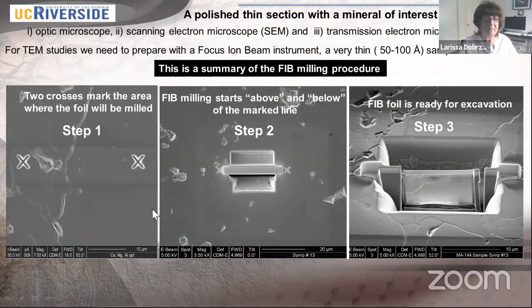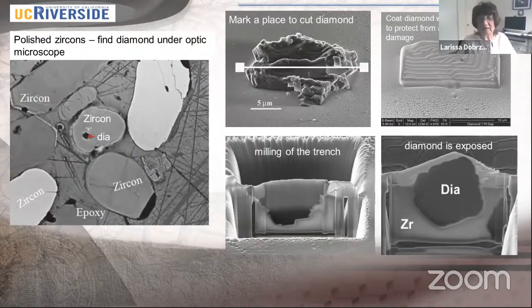You have a polished thin section with a mineral of your interest. You first look at it with an optical microscope and choose the area of great interest for your research. Then you bring it to the scanning electron microscope, and you put two crosses where you will study your material. It's a line, so when you come to the focus ion beam, you already have this mark and find the place very easily. Then FIB milling will start above and below this marked line, this is step 2. Then the focus ion beam foil will be prepared. You see here, finally, you have the plate, very, very thin. It's 10 by 5 microns, but the thickness is 50 to 100 angstrom. It should be very thin to be transparent for transmission electron microscopy.